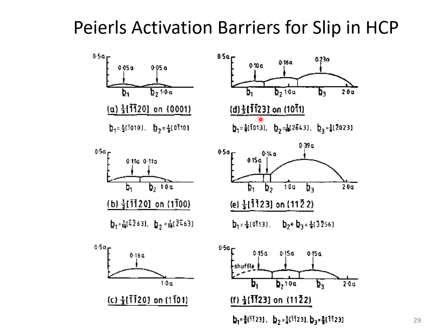So C+A slip on the pyramidal plane has this complicated structure. And as you would see on the videos, in the case of this particular system I demonstrated, you can do this partial glide on successive planes. And what that means is this can now be a twin plane.